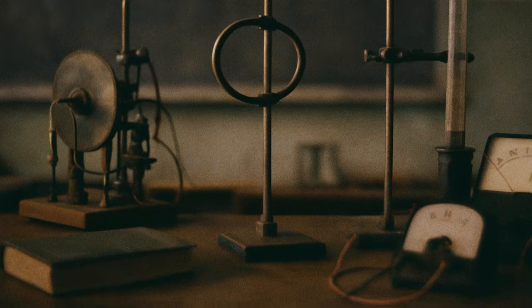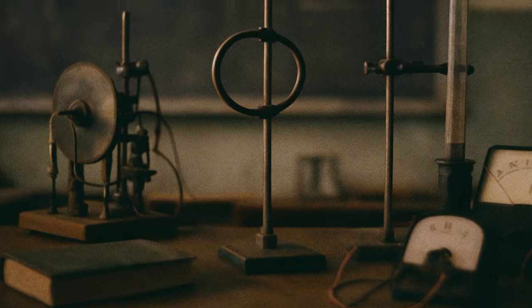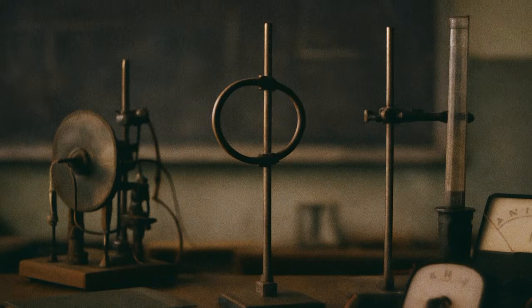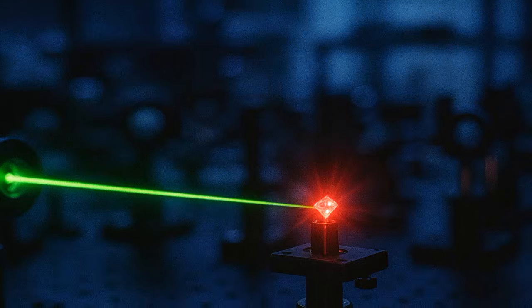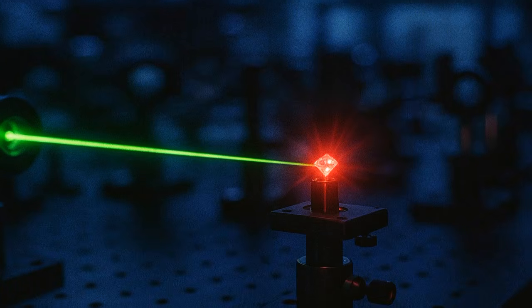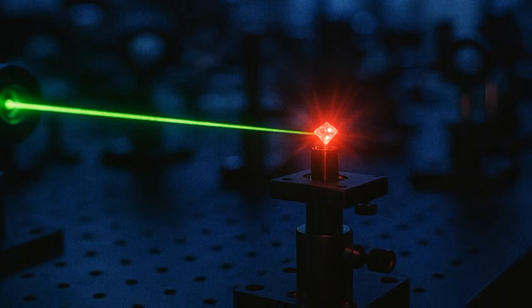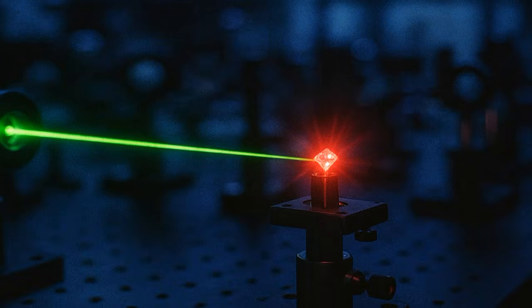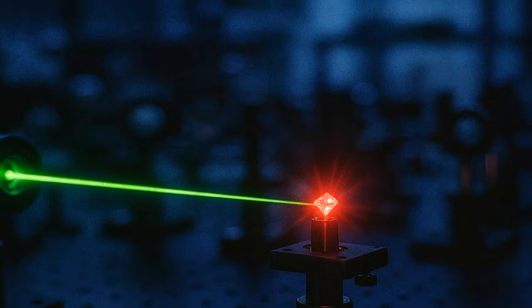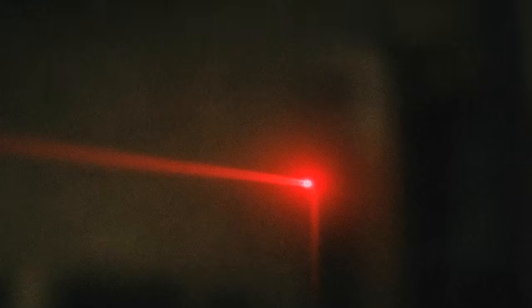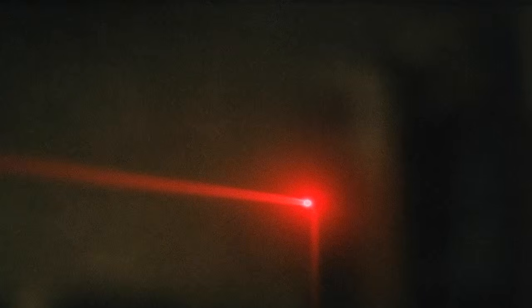The rest of us just see red. Walk into any physics lab with a green laser and a Type 1b diamond, hit it with 532 nanometers. Watch what comes back. 637 nanometers. Bright red light that doesn't stop. Not for hours, not for days. The photoluminescence quantum yield sits at 70 to 80%. That means for every 10 photons you pump in, 7 come back out as visible light.